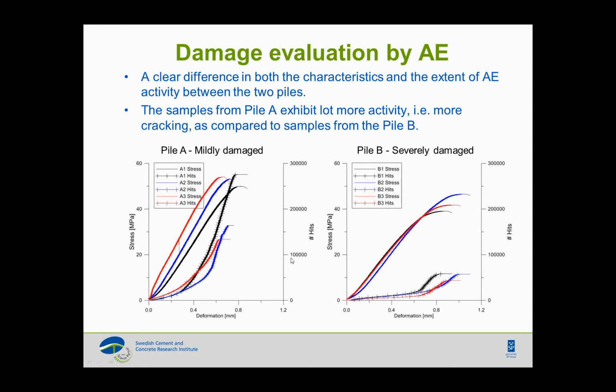So we tried to use a finite element model for these columns, or for these piles. In the lab, we broke down the specimens after testing to identify what type of reinforcement we have and what is the reinforcement configuration, and we tried to mimic exactly the same configuration in our model. So we use the embedded reinforcement in this case. And for concrete properties, we directly use the results from compression tests in our analysis.